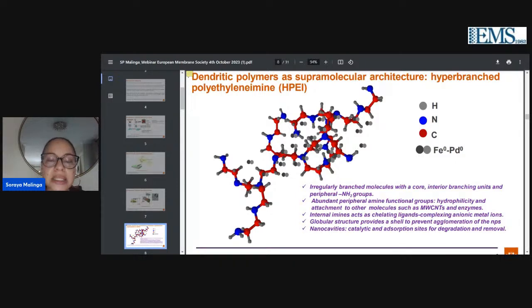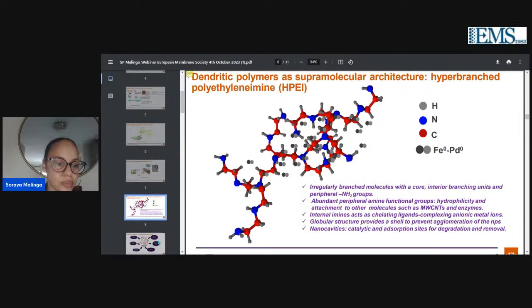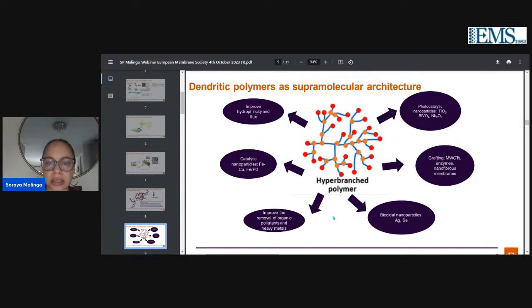The last property that we take advantage of is that this material has nanocavities, or holes, within it that are hydrophobic. So it's a hydrophobic material inside and a hydrophilic material outside. It gives you both properties and you can use them to your advantage, as I said, within those cavities. We have these internal imines that can chelate your particles. Then you'll be able to have your catalytic sites as well as adsorption sites within a concentrated area, and you can have maximum photodegradation or catalytic degradation of your targeted molecule. I think I have summed up the slide in the latter one.